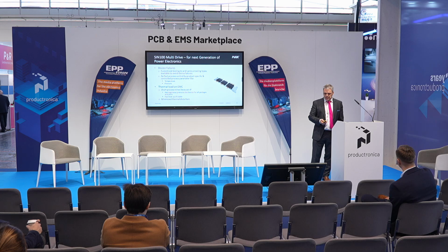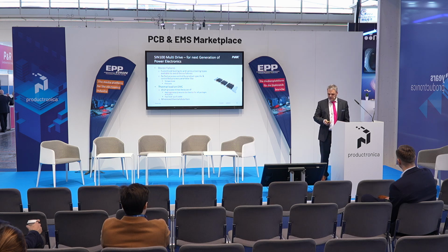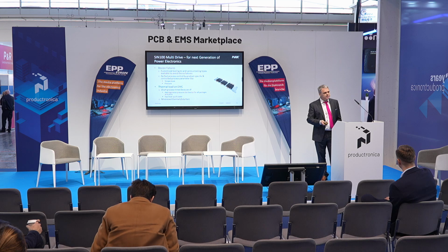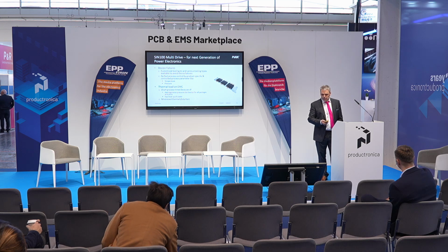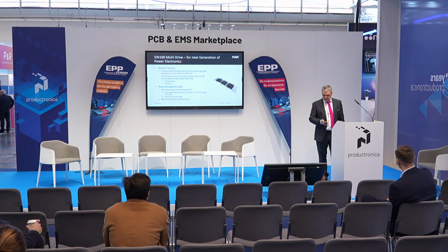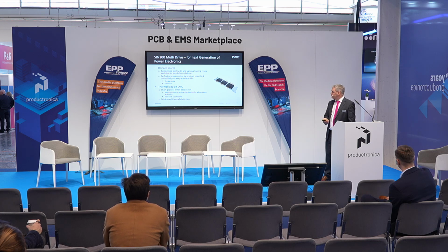We talked about device failures which can happen. We have taken care of that with customized tooling. We have introduced in that machine a temperature and pressure control for the single units, so that we make sure we have the right parameters for the sintering. We have short cycle times, because we can do a fast heat up of the cooler, for instance, and we control the pressure quite homogeneously all over the parts. There is also care taken for minimal thermal distortion between your package and the cooler.